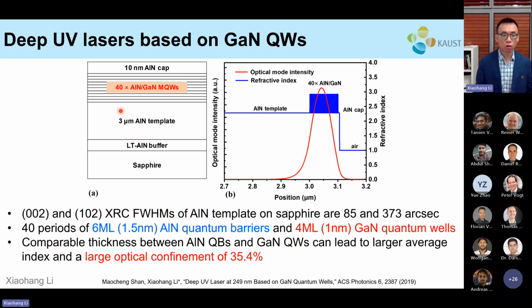We grow this structure again for optical pumping on a sapphire substrate. We have a 3 micrometer aluminum nitride template of high quality, and then about 40 periods of aluminum nitride and gallium nitride quantum wells. We have a lot of periods because we were not sure whether we could get lasing, and we want a large optical confinement because gallium nitride has a higher index compared to aluminum nitride. We grow about 6 monolayers of aluminum nitride barriers and 4 monolayers of gallium nitride quantum wells. Eventually we have an optical confinement of about 35%.